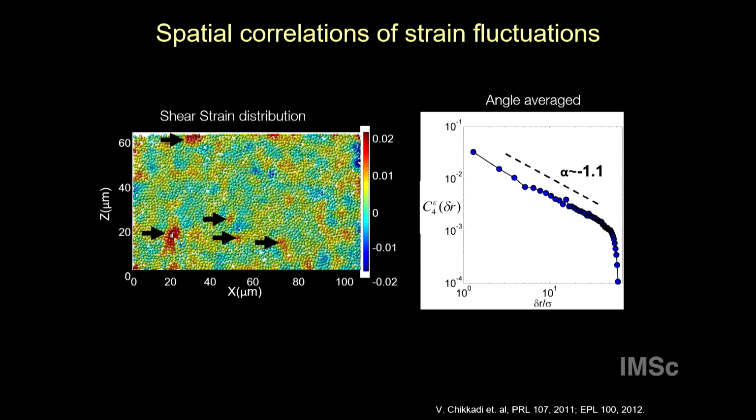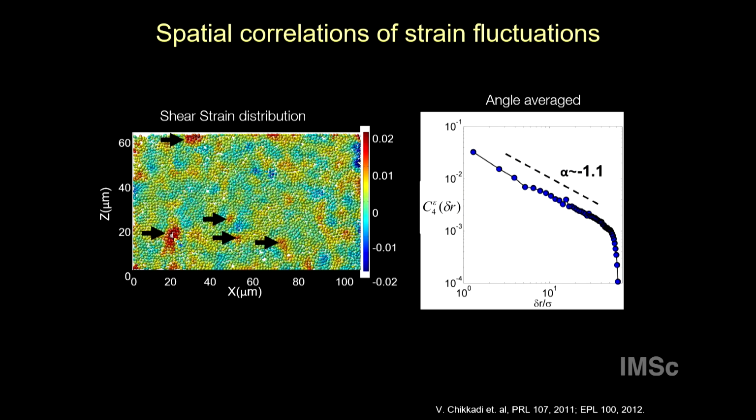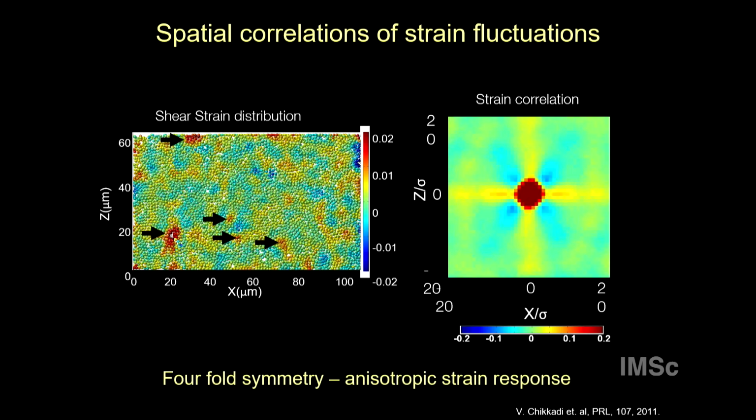We have not really tested whether it is system size dependent or not, but more or less the point where it decays is the distance between the boundaries in the vertical direction. What is C4? I'll explain what that C4 is. It's essentially that we multiply this with cos 4 theta and then take an angular average. If I do a plain angular average now, everything gets washed out. So we use the circular harmonic, 4 theta.